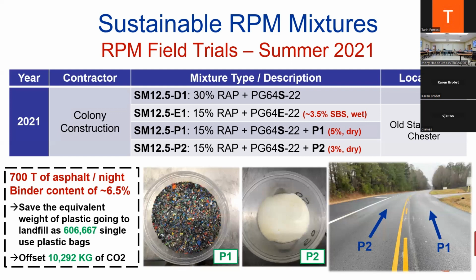And one thing to let you know is that we're putting it at a very low percentage, 5% and 3% of the binder content, not the whole mix. So as part of the mix, it's really less than 1% of the mix that is plastic, but you're still helping. We cannot go and say, okay, we're going to make 10 or 15% of the whole mix plastic. That's a little bit beyond what we can do.